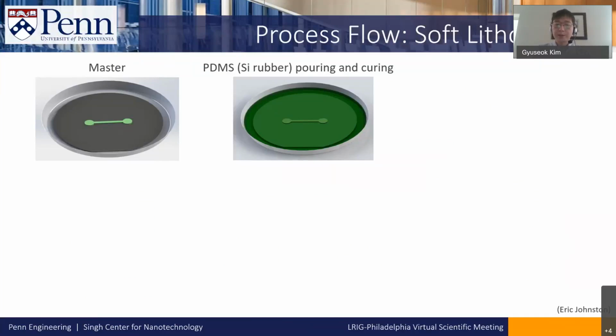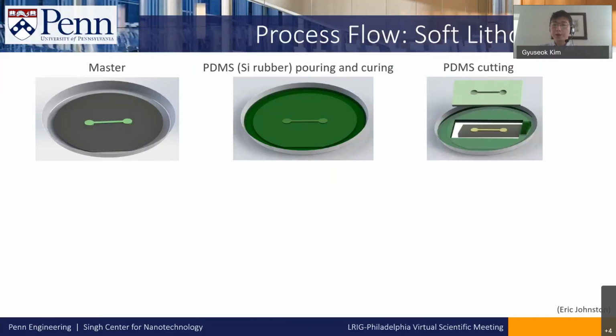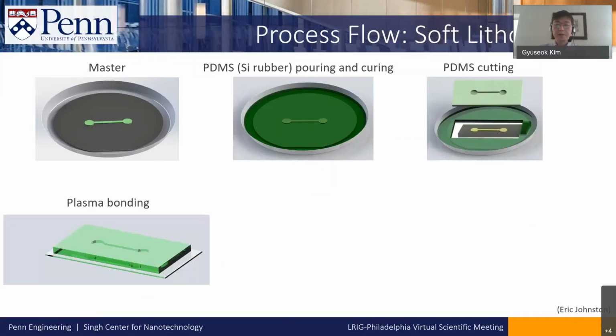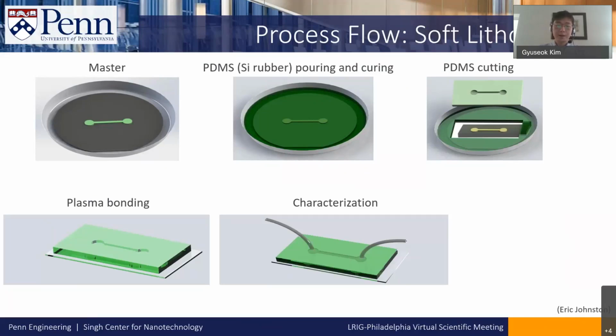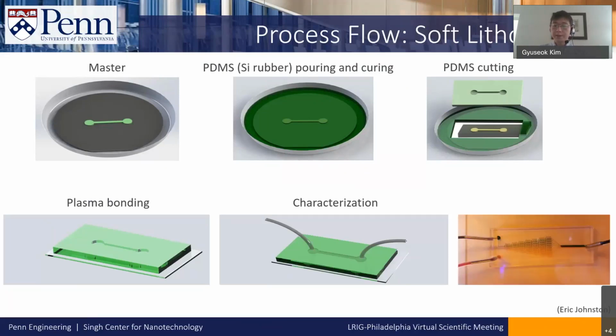Then the next step is to pour PDMS. This PDMS is polydimethylsiloxane. It's a kind of silicone rubber. And then we pour this silicone rubber PDMS and cure. And then we cut this PDMS layer and then do some oxygen plasma to bond our device to the glass. And then characterization. We put some fluids. And this is the final result. And this process takes about 3 hours.